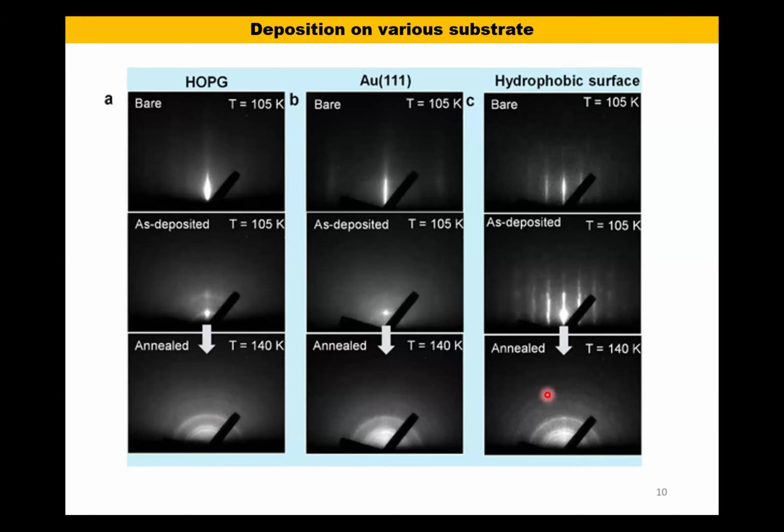But for hydrophobic, it should be reversed because the surface is hydrophobic, so water should be more on top of the ice layer. THF... yeah, the hydrophobic substrate, it is correct, but we are depositing multilayer ice. I told you, 60 nanometer ice. It is dependent on the surface only if you work in the 2-3 nanometer extent. It will work up to 5 nanometer, but above that, it is not dependent on the surface anymore. So you can also do pure water ice on a hydrophobic surface.